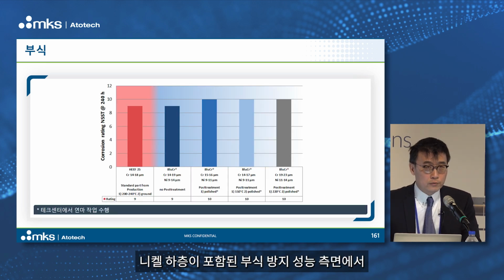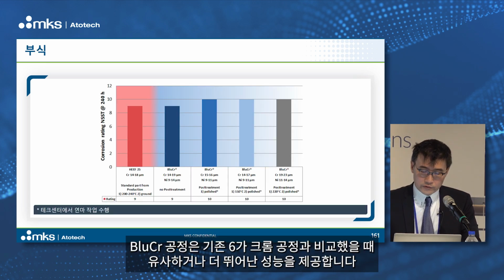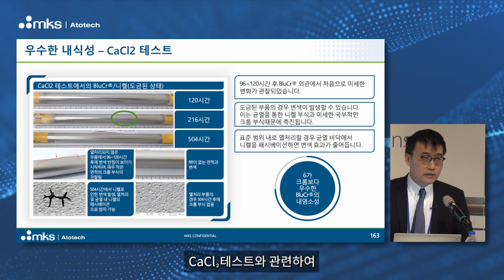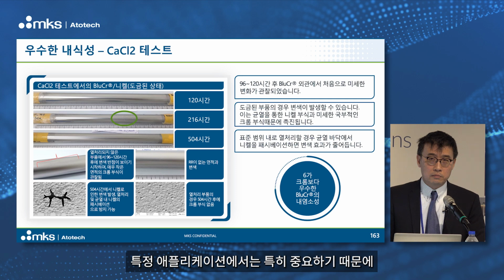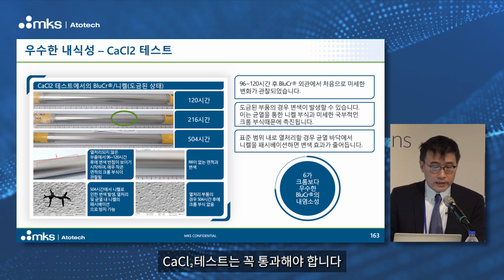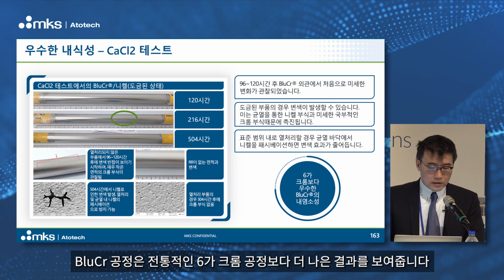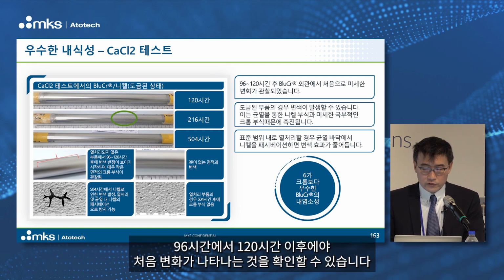For corrosion protection with the nickel underlayer, of course, the BluCr process is comparable or even better than the traditional Chrome 6 process. About the calcium chloride test, especially for some special applications, we need to pass a calcium chloride test. And this time, BluCr is even better when compared to the traditional hex Chrome process. You can see the first change is visible only after 96 to 120 hours.